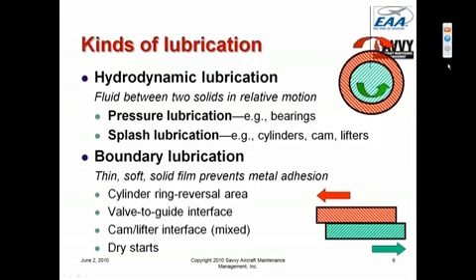Also, when we dry start the engine, that is, when the engine is started after it's sat around for quite a while and most of the oil film has stripped off the parts, during the first few seconds after start, until an oil film is reestablished, we rely almost exclusively on boundary lubrication for that very first part of the start cycle. And in fact, we generate more wear in an engine during the first 15 or 20 seconds after we start it than we typically do for the rest of the run.